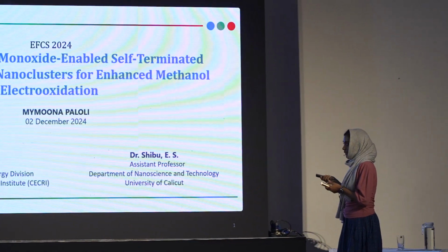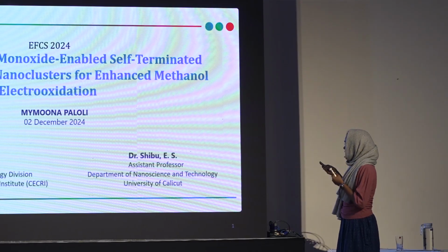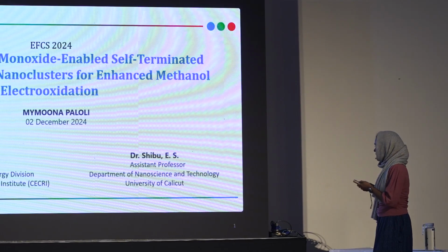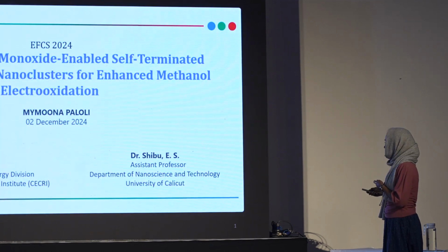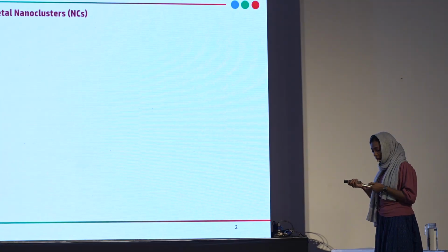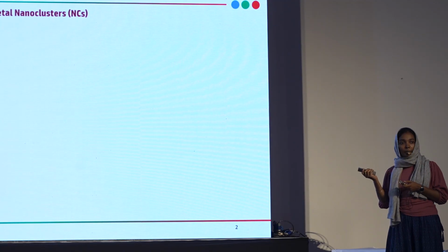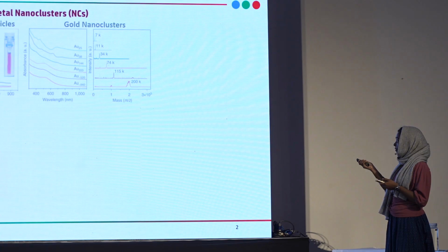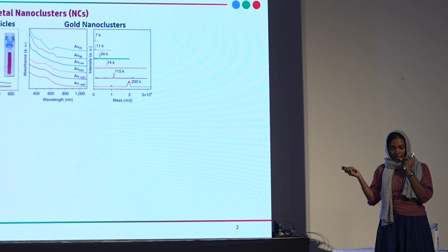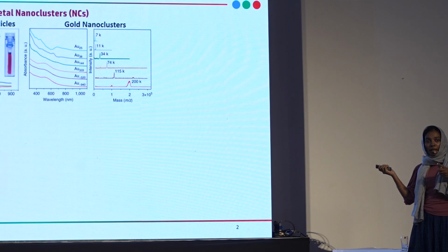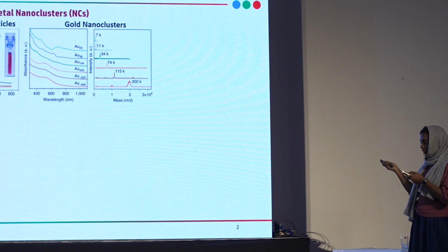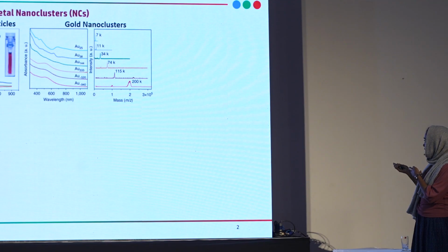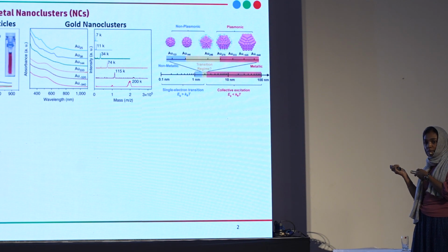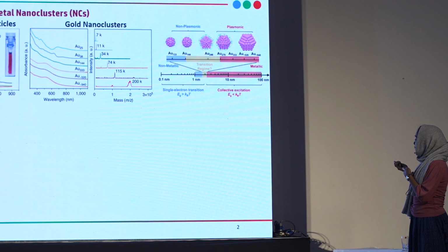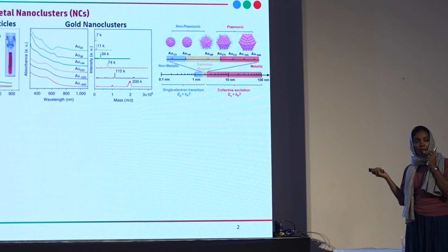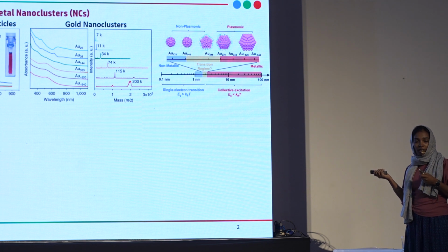Today I am here to present our recent research article on adsorbed carbon monoxide enabled self-terminated Au grafting on Pt6 nanoclusters for enhanced methanol electrooxidation. While moving into the evolution of atomically precise noble metal nanoclusters, significant reduction in the nanoparticle size leads to a pronounced shift from plasmonic behavior to non-plasmonic behavior, which you can see from the absorption spectra. These nanosystems act as a link between the nanocrystal system and molecular chemistry, and this is due to the quantum confinement effect.